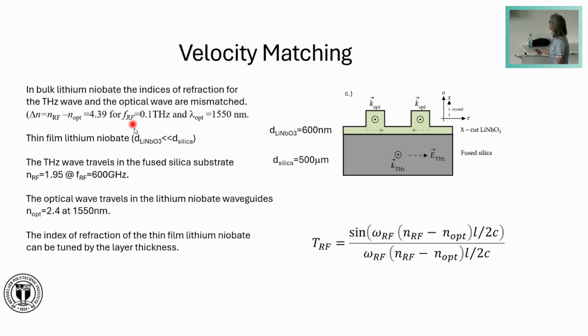If you look at the bulk lithium niobate crystals, they have a large electro-optical coefficient, but a very strong mismatch in the indices of refraction for terahertz waves and for optical waves. Therefore, bulk lithium niobate modulators, which are used in optical communication networks, have a bandwidth limited basically to 100 gigahertz. Most of the commercial lithium niobate modulators from bulk crystals operate up to 30 gigahertz for communication networks. And I know, at least from the US, that there are special military applications, and for this purpose it is still possible to fabricate modulators with bulk crystals which operate up to maybe 110 gigahertz, but this is basically the limit because of the larger mismatch.